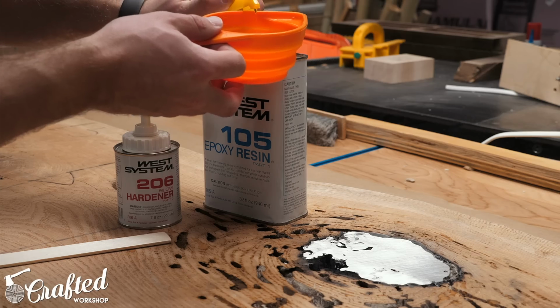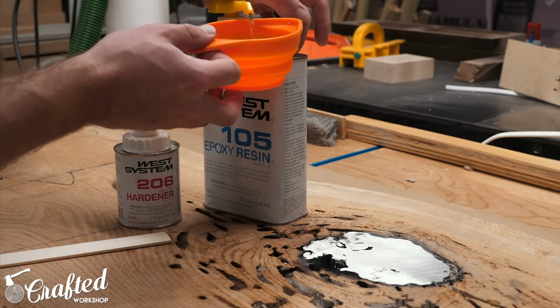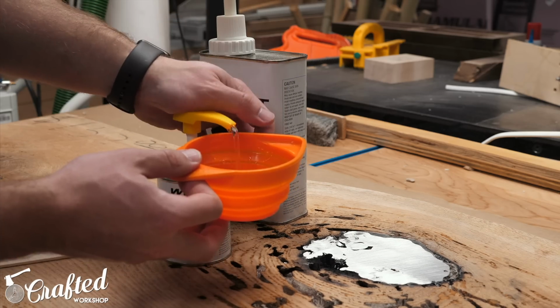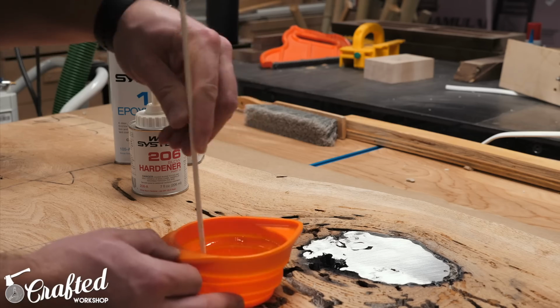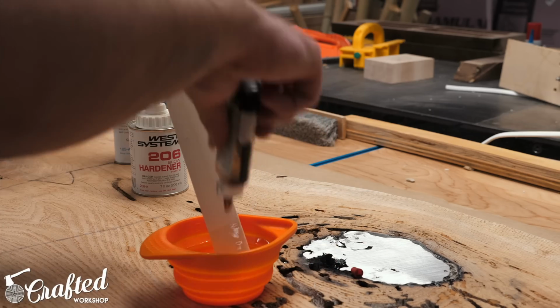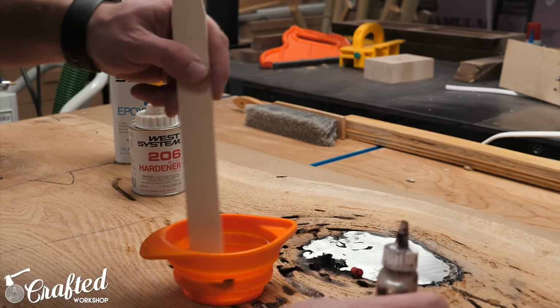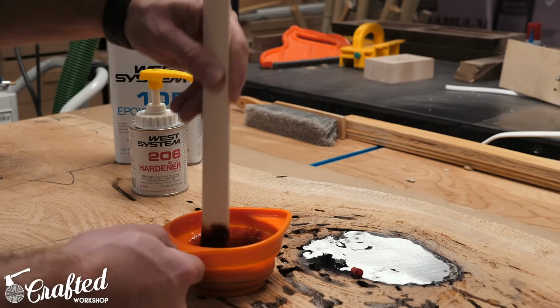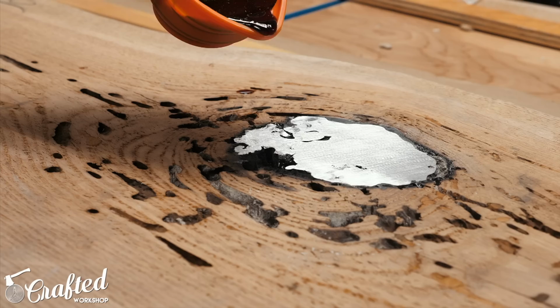I used West System epoxy for this, using the 105 resin and 206 hardener to give myself plenty of open time during the pouring process. I also mixed in some TransTint brown mahogany dye to give the epoxy a little bit of color, since I thought it would blend nicely with the color of the slab.